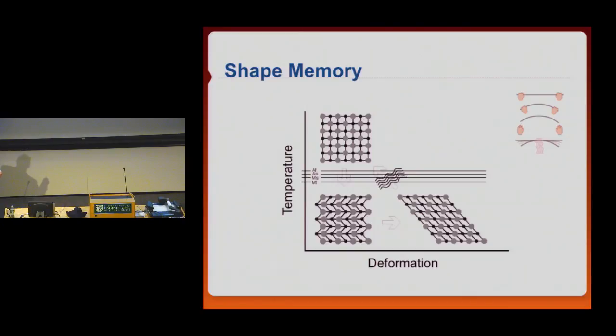And if you now deform this twin martensite, you can detwin by basically moving all the zigs into zag direction. So that goes one after the other, and at the end, you have a fully detwinned structure, which is now deformed, and it stays deformed until you heat it back up over this transformation temperature, and because the atoms still have not changed their location, it finds its way back to its original shape. So this is what we call shape memory or thermal shape memory.